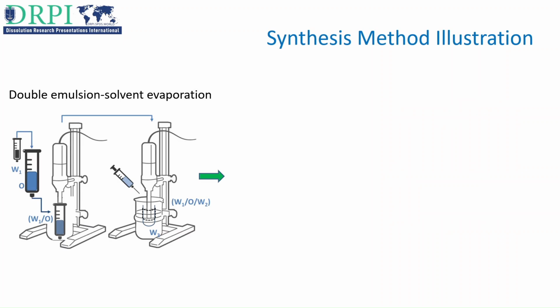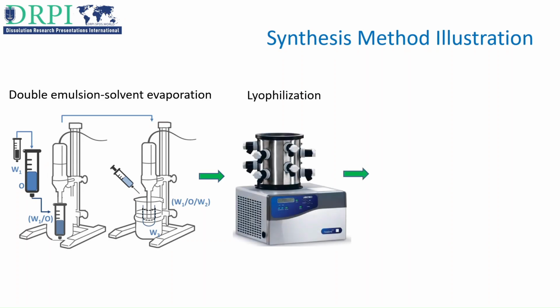This illustrates the microsphere synthesis method. In this study, microspheres were synthesized using the double emulsion solvent evaporation technique, as leuprolide acetate is a hydrophilic substance. The primary aqueous phase consisted of leuprolide acetate and gelatin. The organic phase consisted of PLGA and dichloromethane, and the secondary aqueous phase was a PVA solution. After emulsification, microspheres were collected, filtered, and lyophilized by freeze drying.